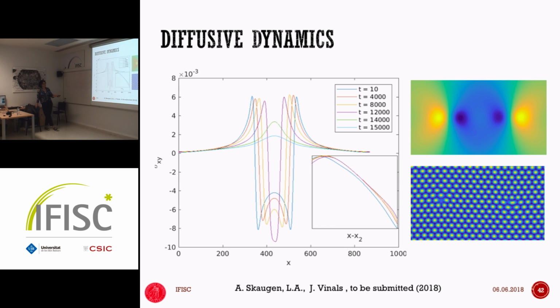in this case here, and you plot it in a log-log scale, you see that at the beginning you might have some sort of scale invariance because we start with the stress field induced by putting two dislocations in the system. We don't let them come up. We know that the phase field is also able to produce topological defects, but then you have to do a different scenario. In this case, we just start with two dislocations, so we put them in as topological defects.